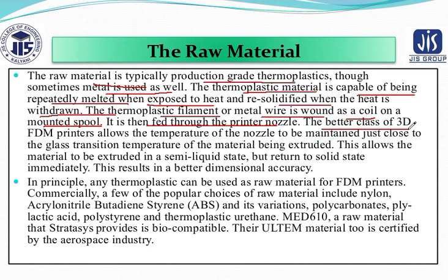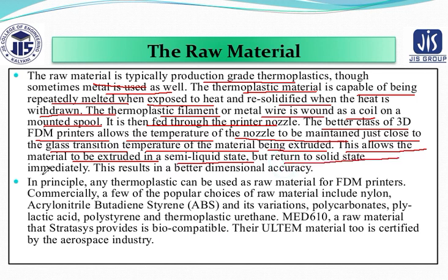Now the better class of 3D FDM printers allows the temperature of the nozzle to be maintained just close to the glass transition temperature of the material which is being extruded. This also allows the material to be extruded in a semi-liquid state, but return to solid state immediately. This results in better dimensional accuracy also.